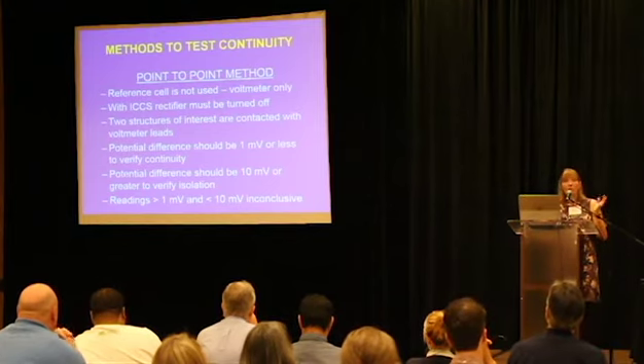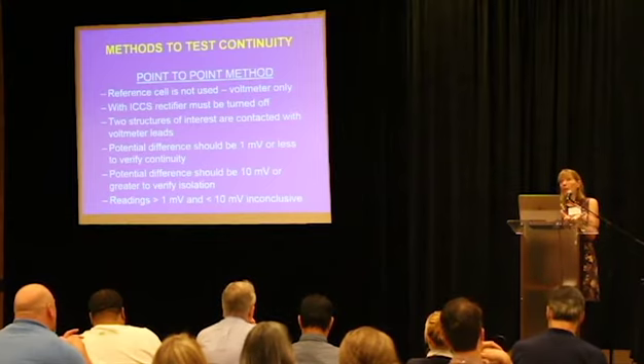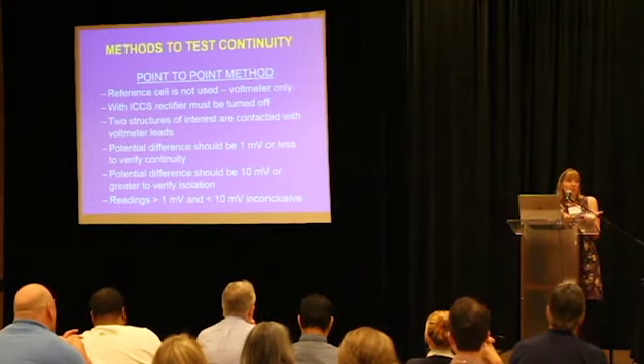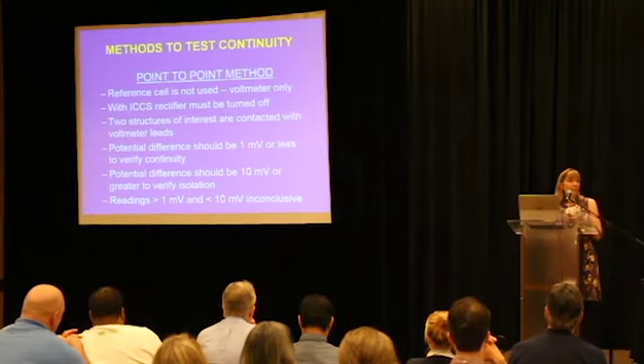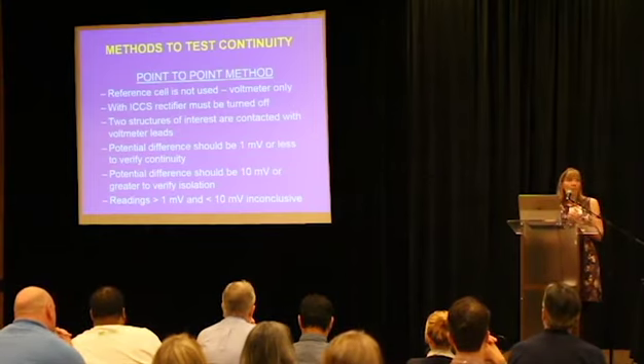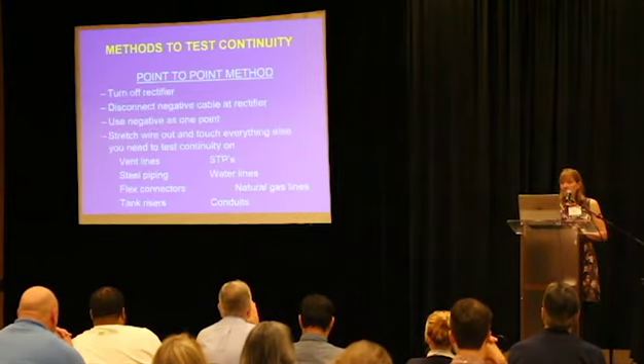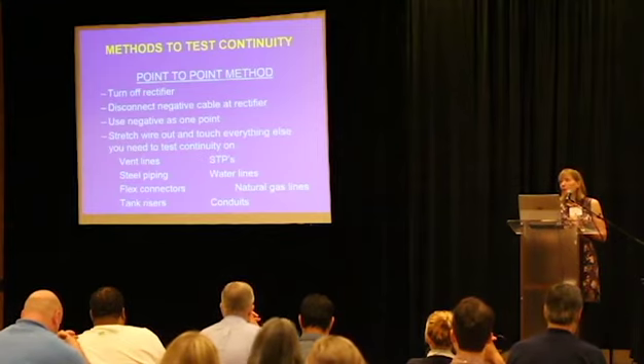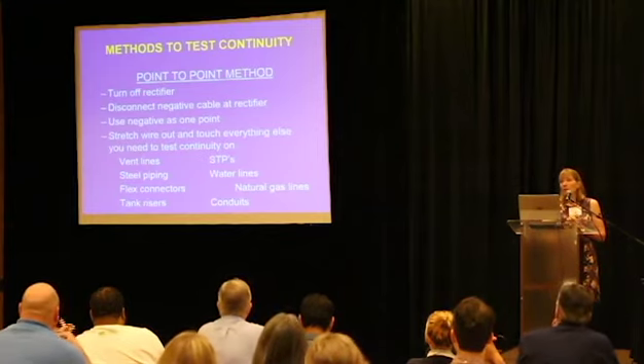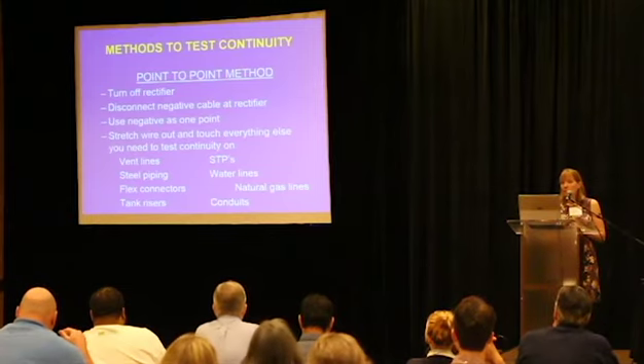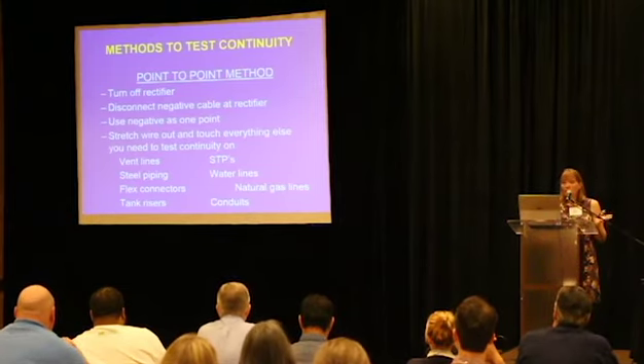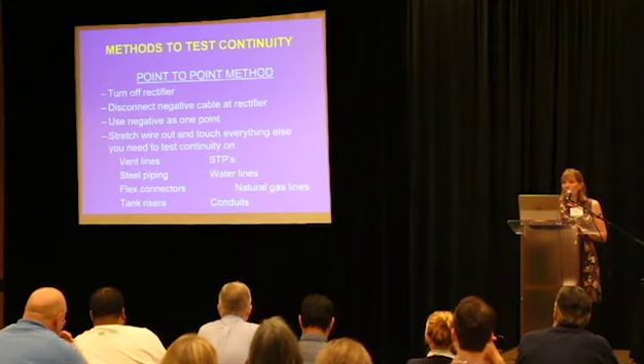If those numbers are greater than 10 millivolts apart, and you'll know because you don't even have to do any math, you're just looking at your meter. If it's more than 10 millivolts, they're isolated. Now for an impressed current system, that would be bad. If it's a P3 tank, that would be good. If they're doing this at a rectifier, the rectifier should be turned off. Again, that's to minimize errors. And we recommend testing for continuity between everything.